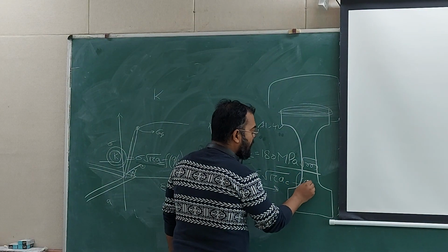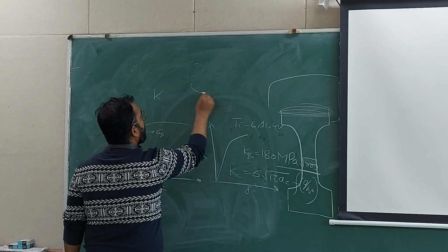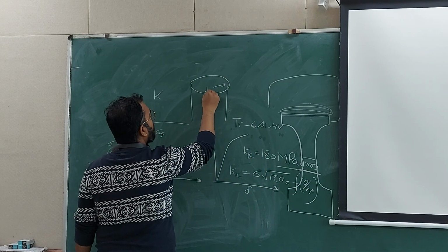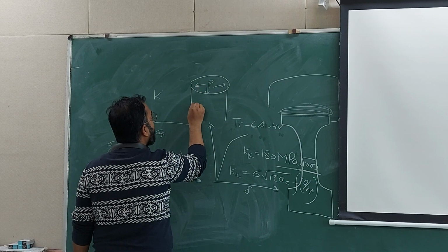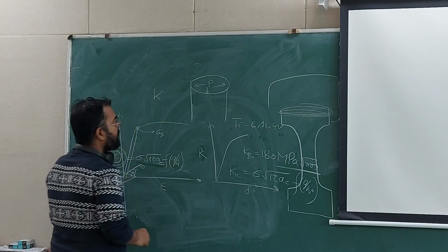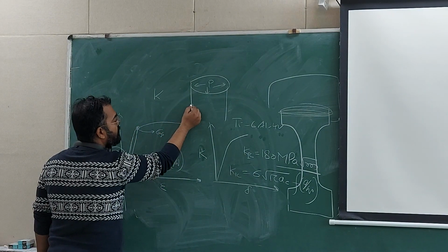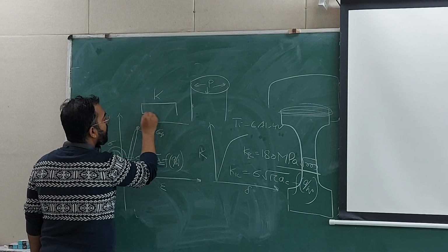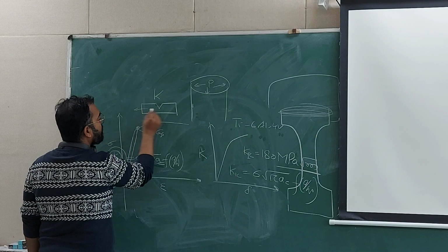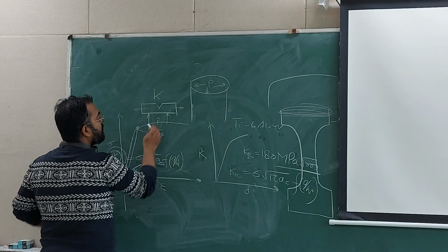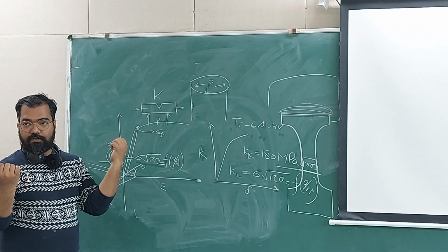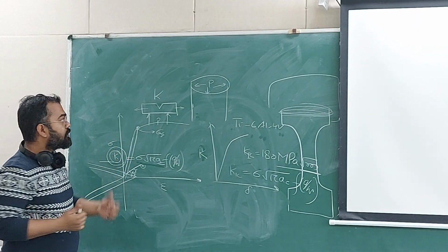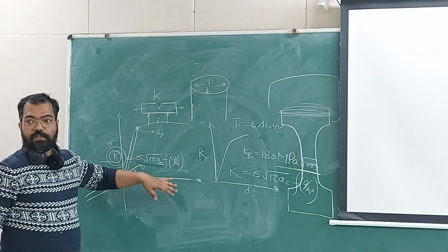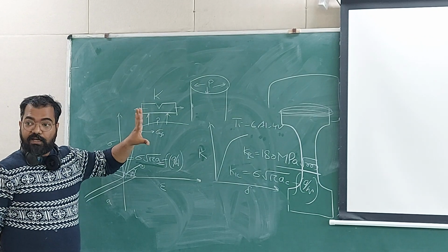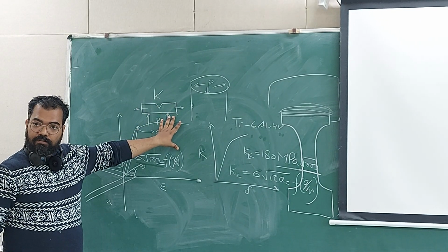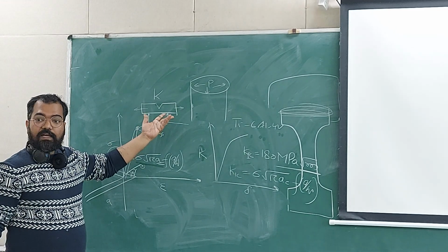If I have a pressure vessel which is internally loaded by pressure, then if I take a small element on the outer radius of the material, and suppose I have a crack like this, I can imagine this is going to expand and bend because of pressure, a small element of that. So this is going to be in mode 1. Even if it is not, the crack can be a little tilted, but the worst condition will be mode 1, so that takes care of the factor of safety there.